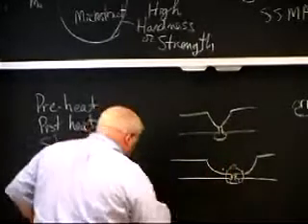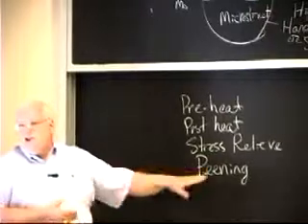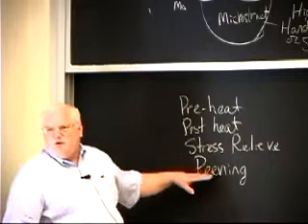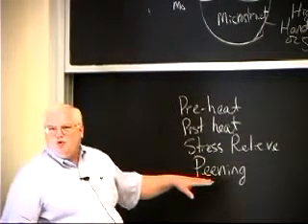You can peen the steel, which basically means you go in there after you make a pass and hammer the surface to introduce surface compressive residual stresses, mechanically stress relieving by peening. We believe that's how they welded the armor plate in World War II, but I told you before, we don't know how they weld 10-inch, 14-inch thick steel anymore. We don't do it.